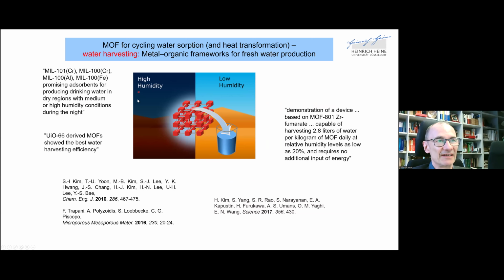And this low humidity is, for example, even existing in desert climates, especially at night. At night, you have a little bit higher humidity than daytime. So you can then absorb the water at night in the MOF and release it again during the daytime when you have the sun giving you the heat of desorption. And thereby you can harvest water in an environment where you have no natural water, or you have problems obtaining clean natural water. So the work of Yaghi points that out, and some other groups have done research in this field also. I will not comment on that any further.